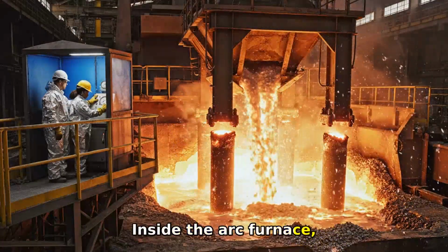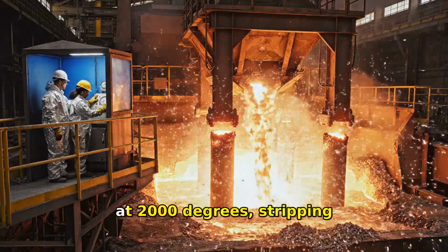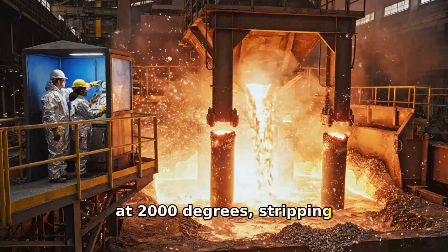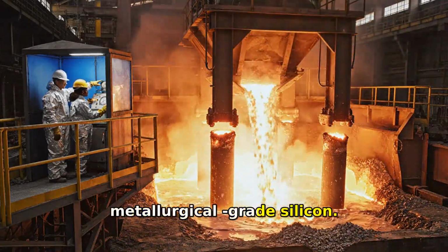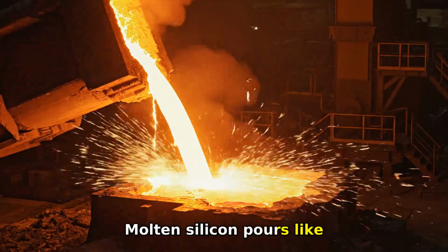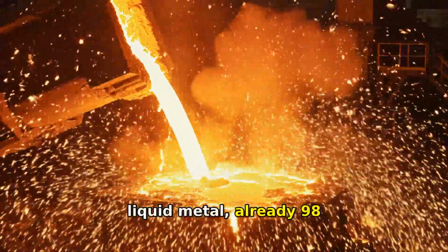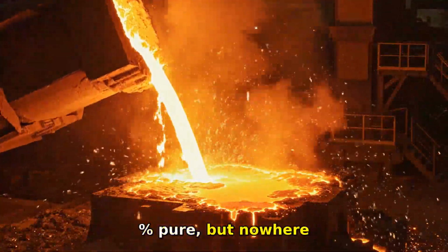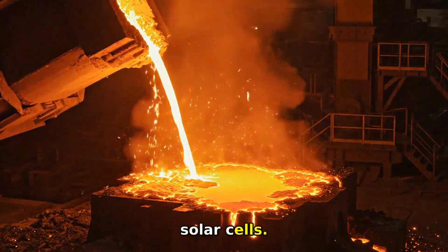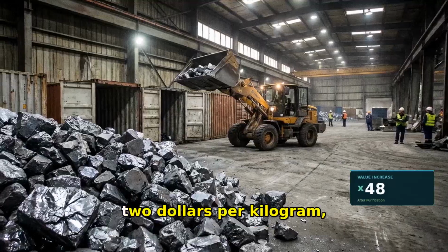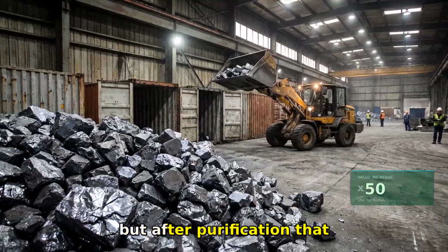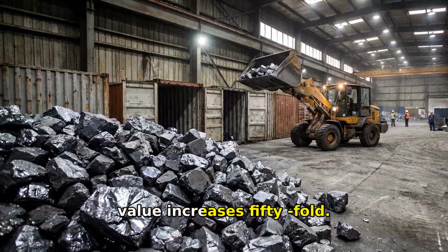Inside the arc furnace, crushed quartz meets carbon at 2,000 degrees, stripping away oxygen to leave metallurgical-grade silicon. Molten silicon pours like liquid metal, already 98% pure, but nowhere near clean enough for solar cells. Metallurgical silicon is worth $2 per kilogram, but after purification, that value increases 50-fold.